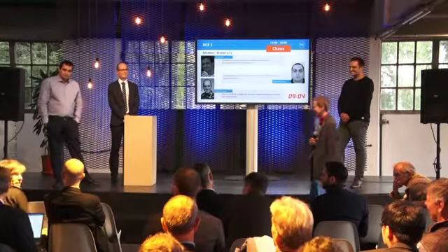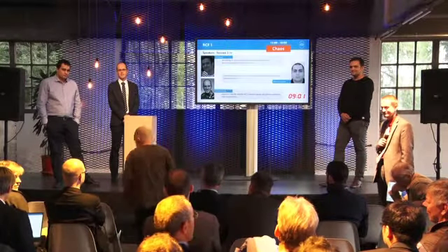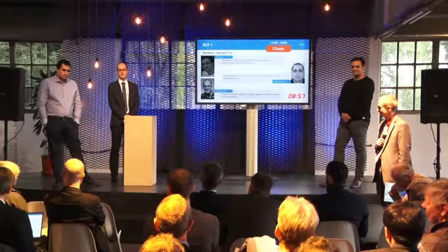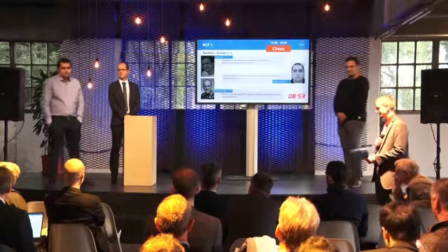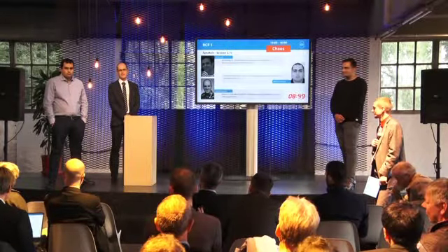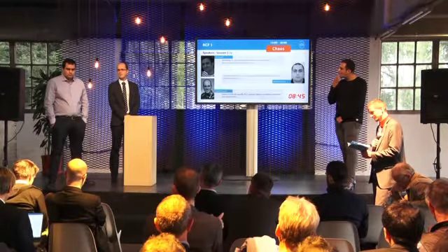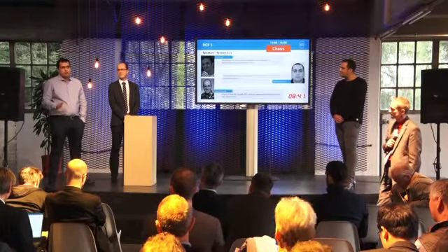Another question here. If we have time, you were using the pressures from the SIMPACK, right, as input for your finite element calculations, and that is elastic, right? So your pressures are extremely high, and so I imagine that your plasticity calculations overestimate the amount of plastic deformation. Actually, we used the stresses from SIMPACK, and we use effective plasticity models. So we use a contact model which takes into account the plasticity, so we limit the stresses a little bit, and the contact surface is a little bit larger, to get the right forces. So is it somehow empirical, or how do you do it exactly?